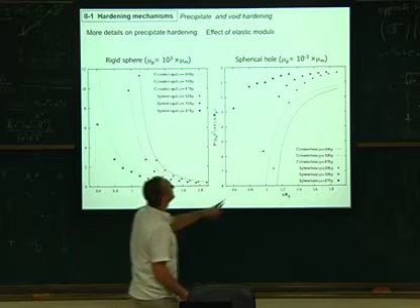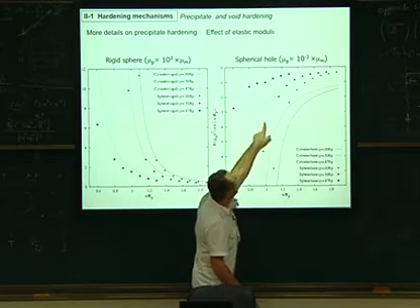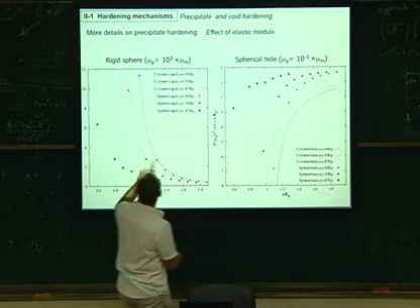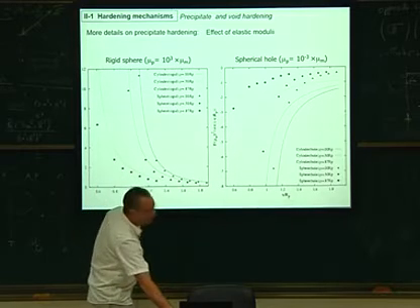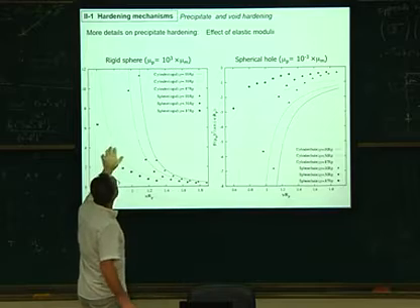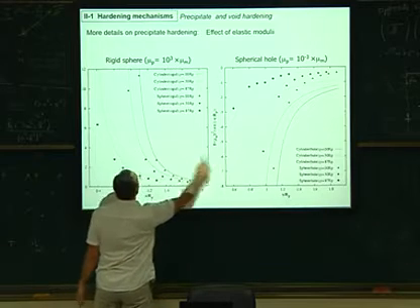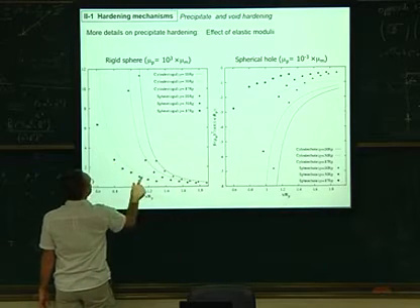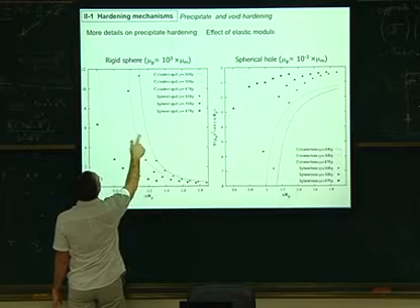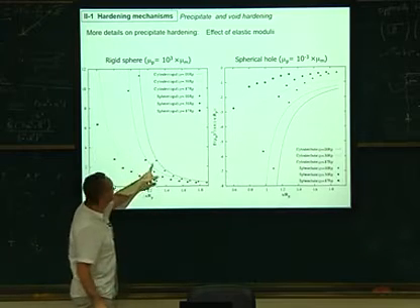So here I compared the solution for the hole, this is the point here, to the cylinder. For the cylinder, we knew that it matches. You see the cylinder was before, so we know we matched the solution very well. And now if we take a sphere, whether it's rigid or a hole, you see that these are the DD points, and these are the analytical cylindrical case.